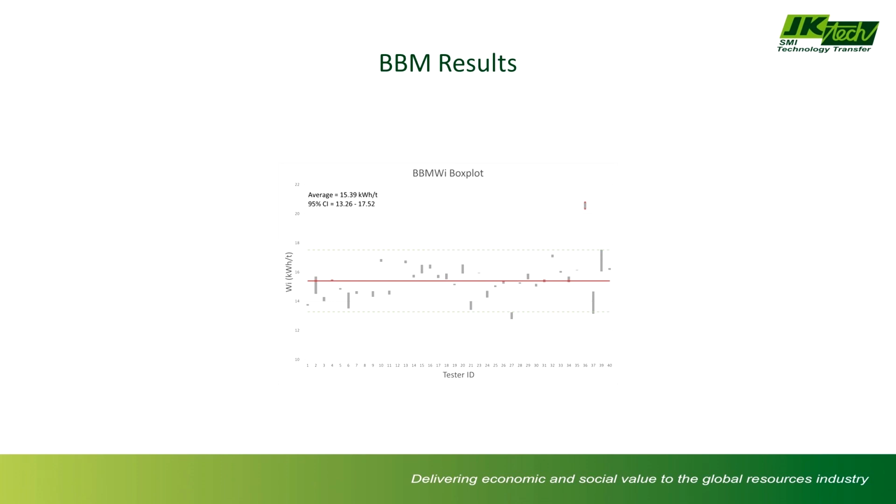Again, we do have an outlier, determined to be an outlier via the Grubbs test. And I believe, if I remember correctly, that one actually just came down to a data input entry. It came in the calculation method for the P80. They'd made a little typo in their spreadsheet in the P80 calculation. I did discuss that with them, and once that was corrected, it did get pulled back down, but we left the results as is, their analysis, and because there was a known issue, we took that one out for the further analysis for the average and the confidence interval.